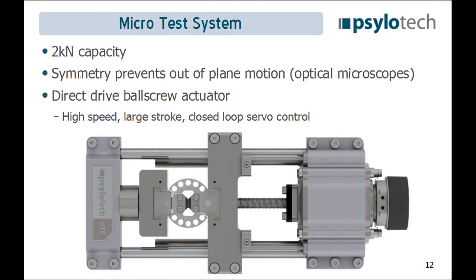I'm just going to go through a few specs of the systems so you can have an idea. This frame is the standard model. It's a 2 kilonewton capacity. You can see the four inductors that are used for the displacement sensing. But we're very careful to keep everything symmetric. The ball screw is on axis, the direct drive ball screw, so that the nut is directly tied to the motor's rotor. And everything is completely symmetrical. The ball guides are in the plane of loading. Everything is on axis, which is the exact reason why things don't move out of plane when you run the test. So that symmetry is very critical for keeping things in the field of view of an optical microscope.